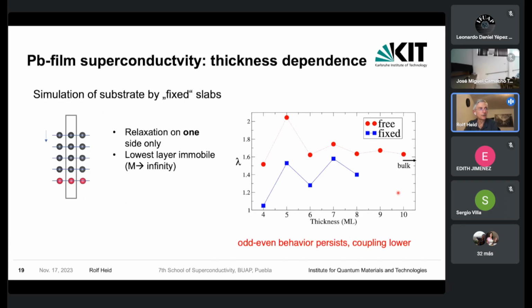And at least a little bit to mimic the presence of such a substrate, what we have done is that we have performed similar calculations, but keeping the lowest layer of such a slab fixed, so to say, keeping them immobile and taking the mass to infinity. And then repeating all the other calculations of electronic, harmonic, and electron-phonon coupling properties. And we find in this so-called fixed slab geometry that indeed the coupling is reduced compared to the free slab, and we still see this oscillatory behavior.